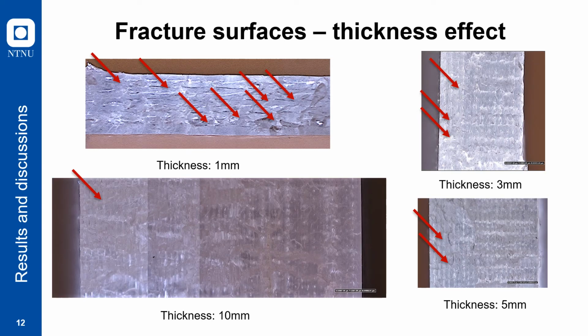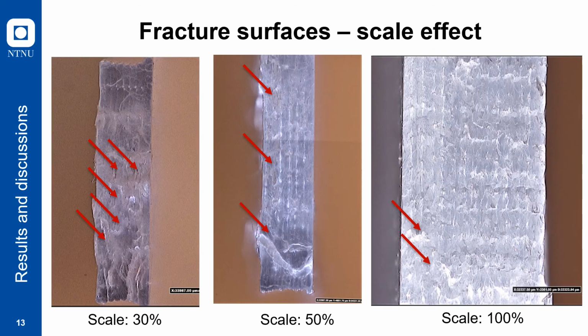And these are the fracture surfaces with the thickness effect. As you can see, the arrow indicates here there are some defects such as voids during the fabrication process. As you can see, visually, if the thickness is getting larger, then the defects will decrease. Similarly, for the scale effect, here we have presented the scale from 30% to 100%. As you can see, for the 30% specimen, there are many more defects during the printing process than for the rest.